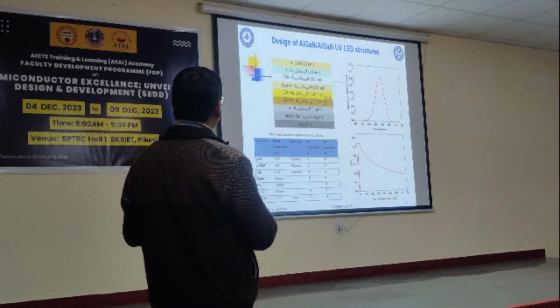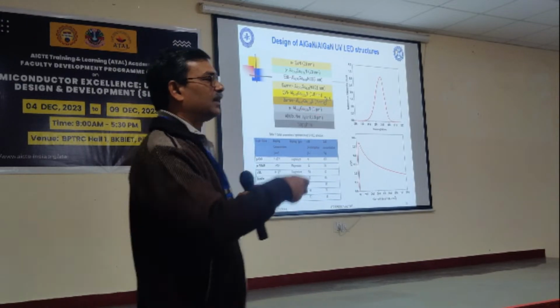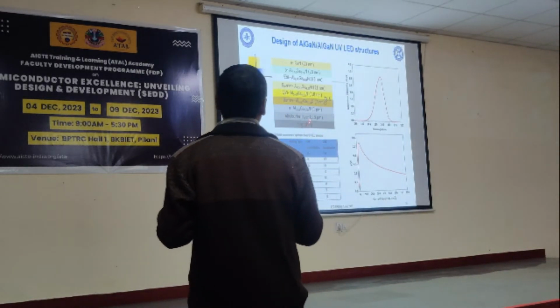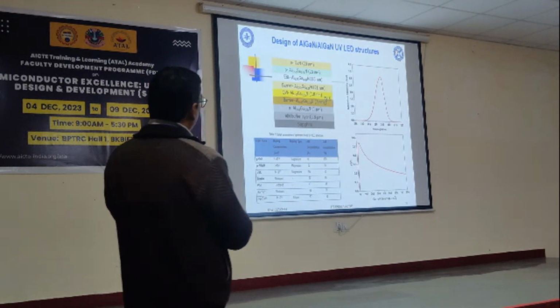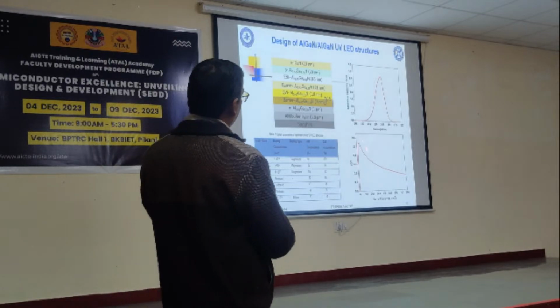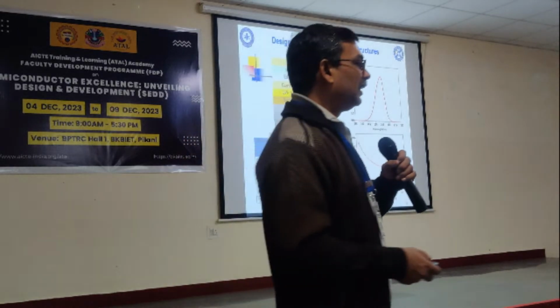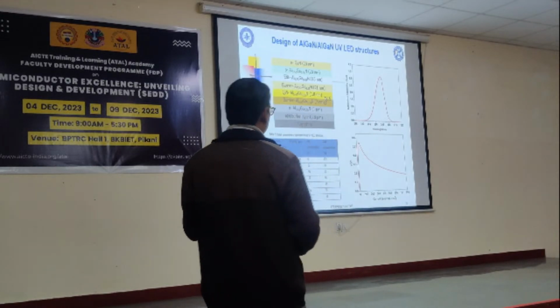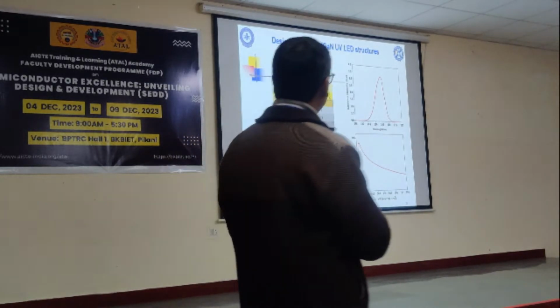So in this case, the quantum well region aluminum composition is 47% and the barrier is 62%. So a higher barrier aluminum composition means a high band gap, so that can act as a barrier, and low means that can act as a well. And depending on the aluminum composition, we can have the emission wavelength. So in this case, the emission wavelength is around 265 nm, which is very much required for sanitization purposes, particularly the UVC region. So we can design accordingly, and obviously we can fabricate.